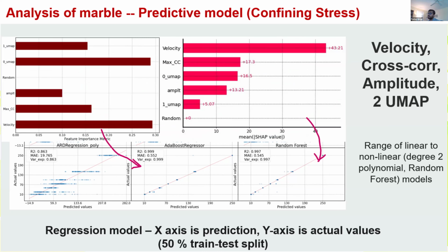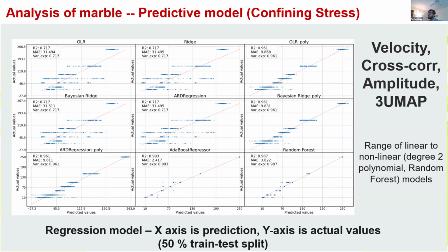We can look at which features are most important for the random forest or AdaBoost models. The exact feature importance is a little bit different between the 2 models, but the key point here is that, yes, velocity matters, yes, cross-correlation coefficient matters, but the UMAP features are also important. UMAP 0 and UMAP 1, the 2 dimensions of the UMAP, are pretty important in being able to get that accurate prediction. And UMAP 0 is more important than the amplitude of the waveform in being able to predict where you are with regards to confining stress. You can do the same thing with 3 UMAP features, and even with a Bayesian, linear least squares regression type model, we can start to get pretty accurate results.